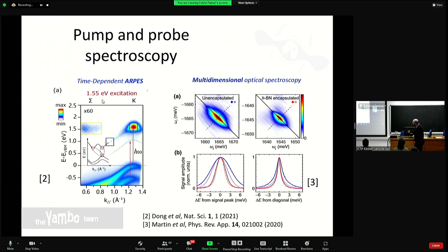Here you see the main diagonal is the line width of an exciton peak, including these inhomogeneities. And instead, the cross diagonal is the homogeneous line width. So it's the pure, perfect crystal line width, more or less. Of course, these are very difficult experiments. And you see, this is basically the cross section in the homogeneous direction. And people found that the line width of the exciton peaks can be reduced by one order of magnitude between inhomogeneous and homogeneous. So this is quite important experimentally.